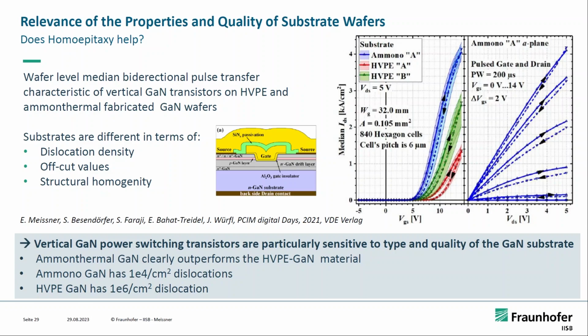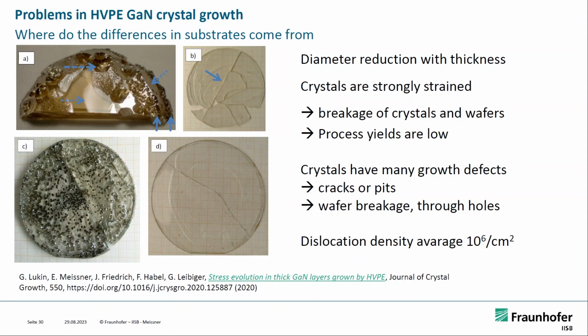So it may help and it may not help. Why is the ammonothermal material different at all? You see that in the HVPE material, we have many issues, like the diameter getting smaller, you create cracks, you can have growth defects. You can have nice substrates, but they are highly strained, and then you touch them and they break.